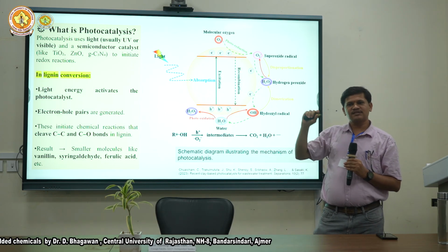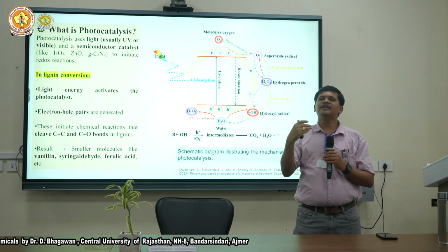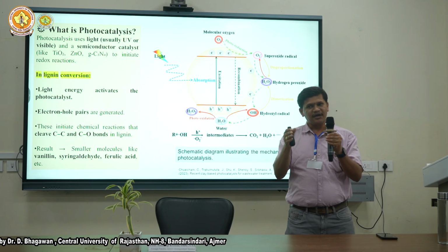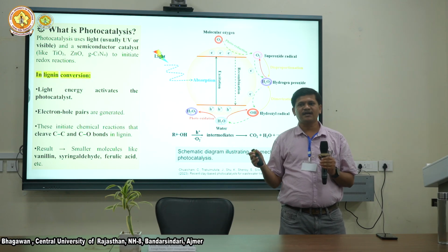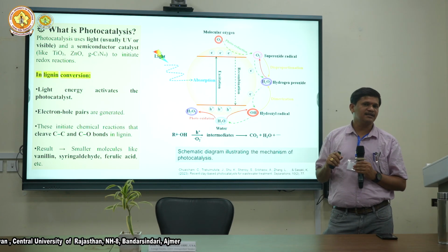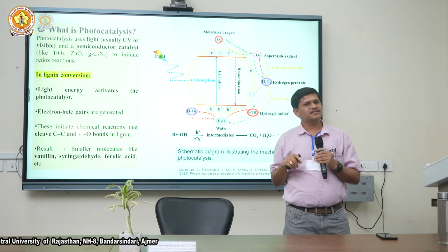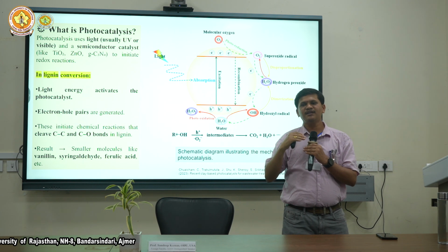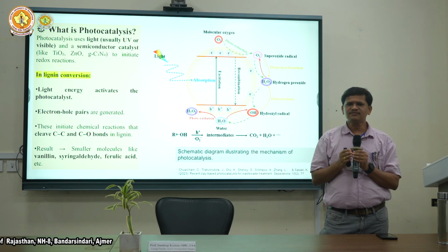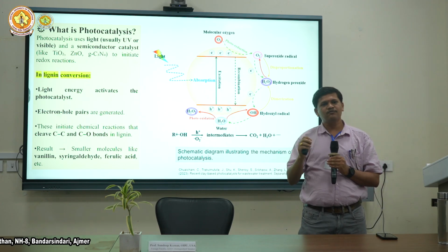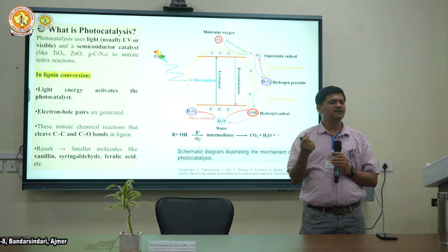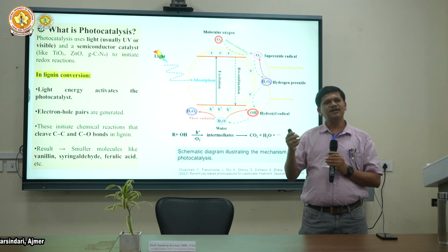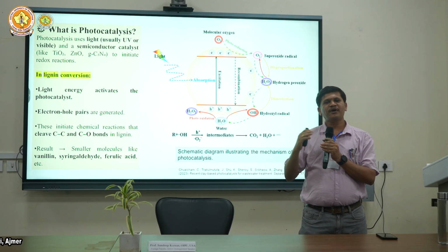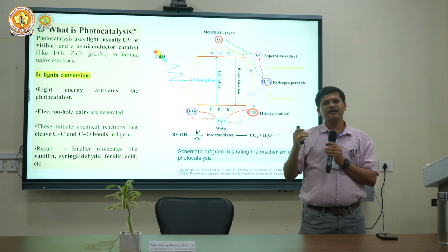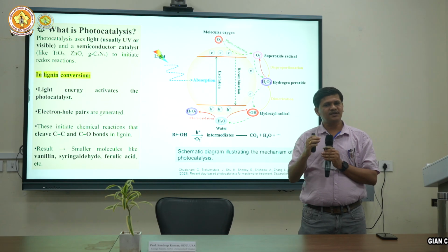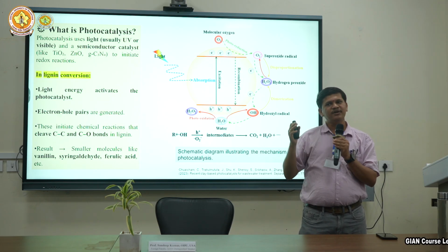But whenever we think about selective component, selective band gap, then we need to design our experiment in such a way that we can reduce this band gap, or if required we can extend the band gap. So that will be for homogeneous catalyst. Suppose at the homogeneous stage it is not possible to maintain this band gap, then we need a catalyst with heterojunction, meaning we can combine. Suppose we thought to use zinc oxide, because zinc oxide is cheaper when you compare with titanium dioxide. So zinc oxide's band gap is higher, 3.2 to 3.3 electron volts. But our requirement is to reduce it to 3.0 or so. So how will it be possible? How can we reduce this?